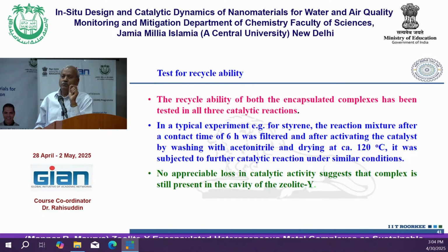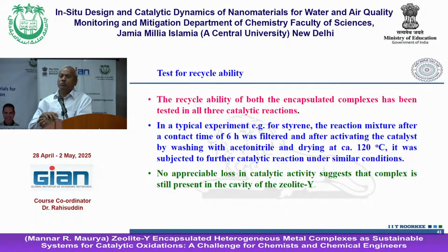Now, the question is recyclability. These catalysts are very good, recyclable. The reason is that they are recyclable under the reaction conditions, and that is important. When you heat excessively, that compound has to decompose. Under reaction conditions means when you have 80-degree, 100-degree temperature for the catalytic reactions in the solvent, the compound is not decomposing at all, because it is entrapped in the cavity. It is just moving in the cavity. It can change its position, but it cannot come out. When it cannot come out, recyclability becomes very easy.